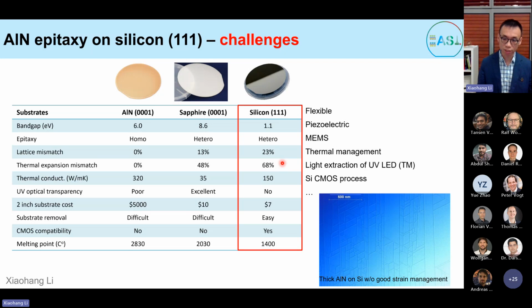The GaN on silicon technology has been developed for multiple decades. And today, a lot of the GaN devices, especially the power devices, are made on the silicon substrate. But the aluminum nitride growth on silicon is still in its infancy, right? So if you don't control the mismatch and the tensile strain well, you end up with a lot of cracks, as shown right here. This is from one of the samples we have grown that has a lot of cracks, which becomes not usable for device applications.